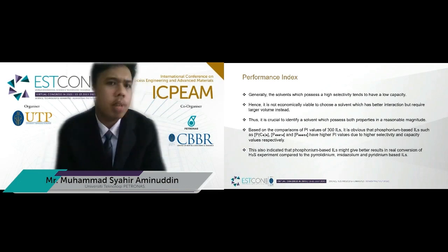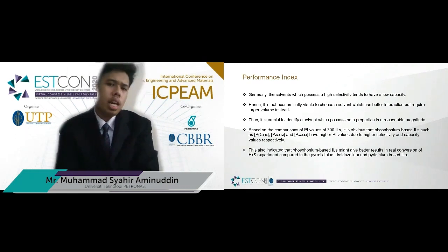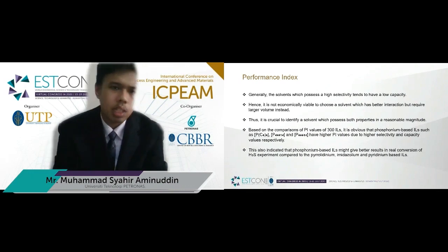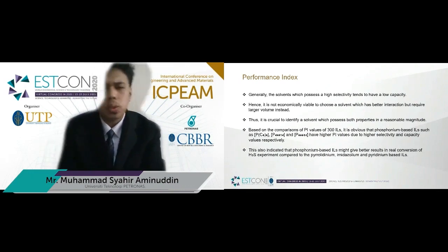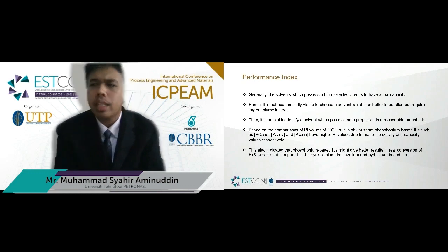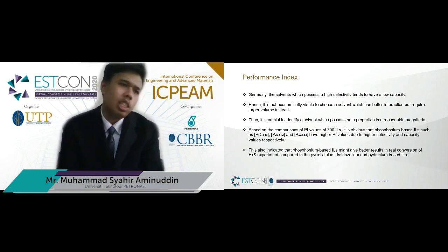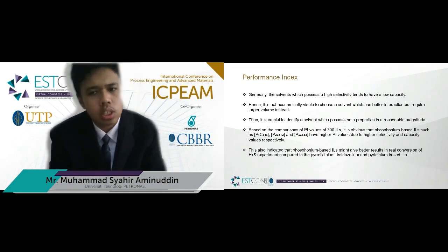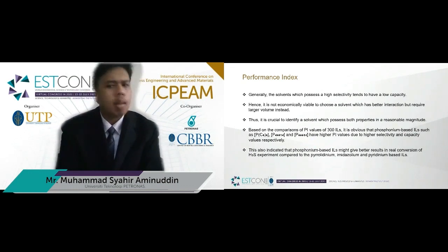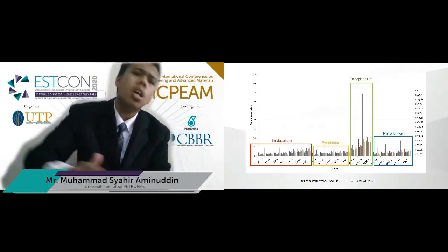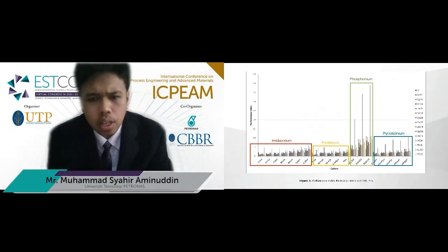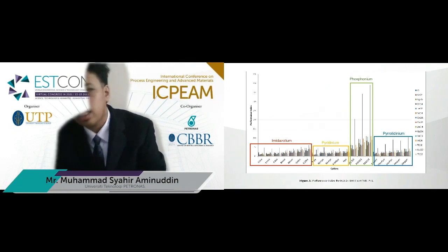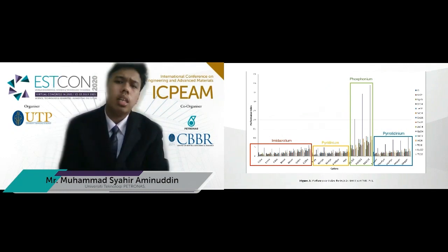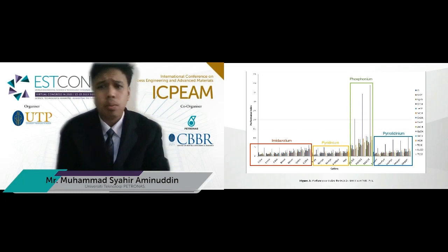Based on comparison of PI values of 300 ILs, it is obvious that phosphonium-based ILs have higher PI values due to higher selectivity and capacity values respectively. This also indicates that the phosphonium-based ILs might give better results in the real conversion of H2S experiment compared to the rest of the ionic liquids. As you can see, this is the performance index for hydrogen sulfide in 300 ILs at 288.15 K. We can see the performance index increases from pyridinium to imidazolium to pyrrolidinium and phosphonium.